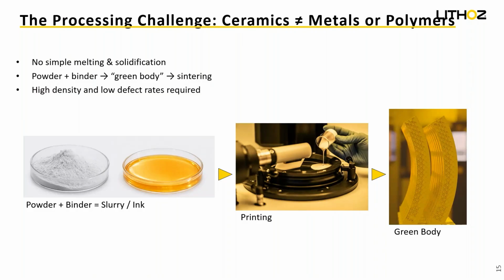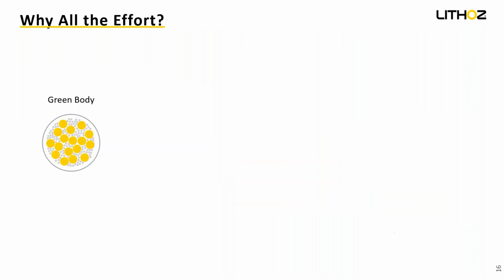If the green body is not printed correctly, for example, if the print is not uniform or the features are not clean, it becomes very difficult to reach high density and low defect rates after sintering. So the entire success of ceramic additive manufacturing starts with getting the first step right. Once we have printed the green body, the real work begins.